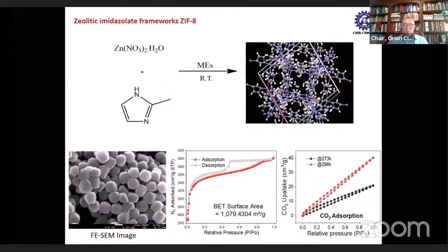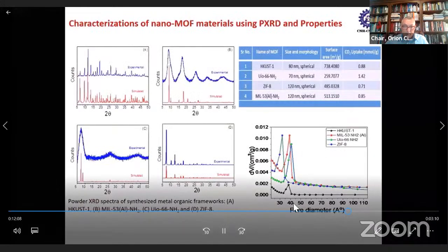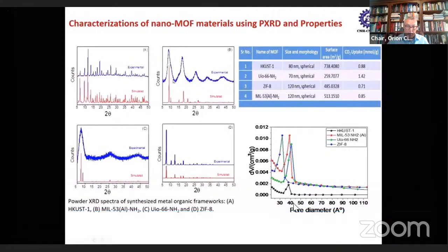Further, we could also synthesize zinc-based ZIF-8 metal organic framework using zinc nitrate precursors. They were mixed in microemulsion systems, and again at room temperature, uniform morphology spherical MOFs with nano size were synthesized, which were characterized for surface area and carbon dioxide adsorption studies. All these MOFs were characterized for their crystallinity and their other physical properties. These MOFs were found to be very good crystalline in nature, and surface area of the synthesized MOFs was moderate as compared to the MOFs synthesized by other conventional methods. CO2 uptake was also moderate for the materials synthesized using these methods.